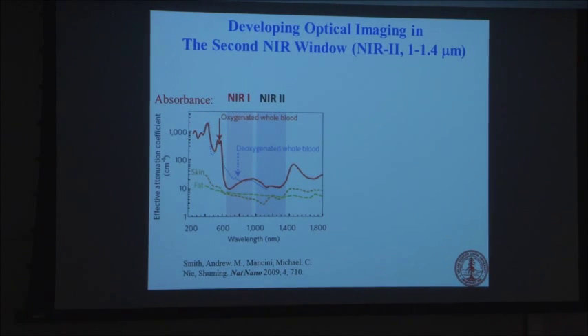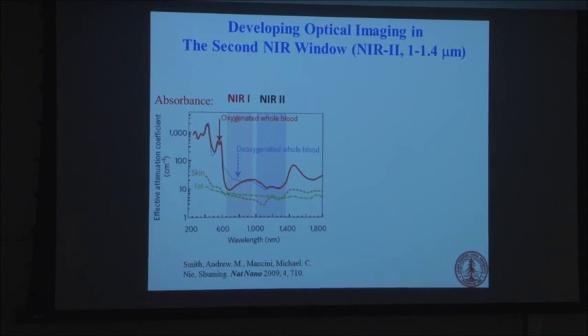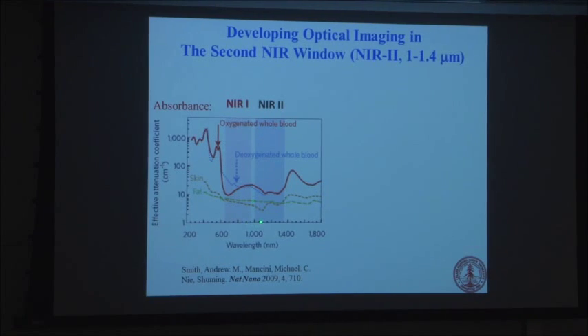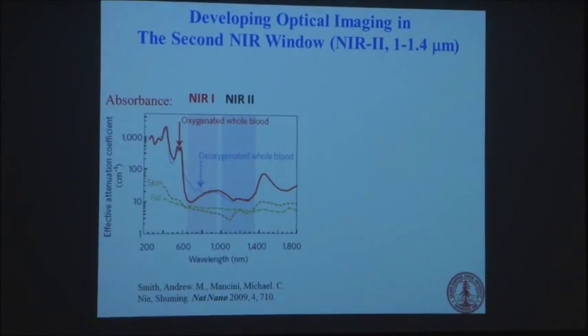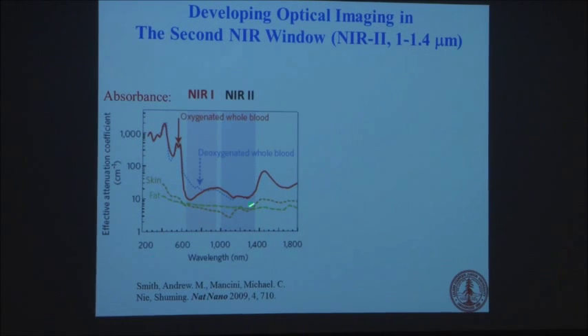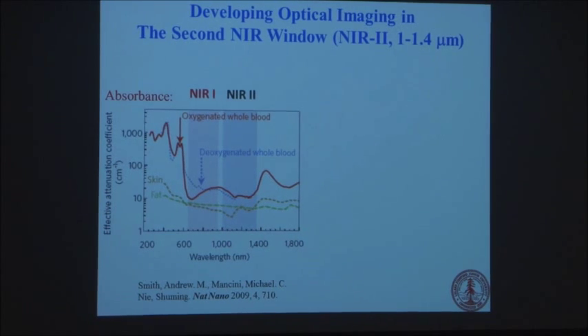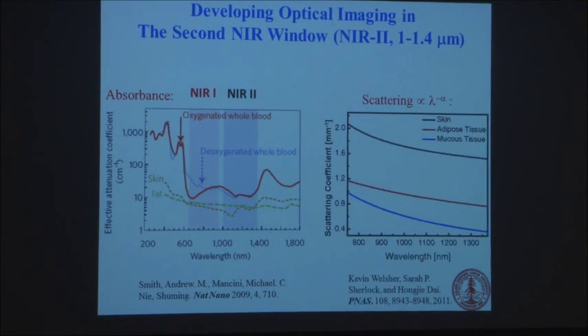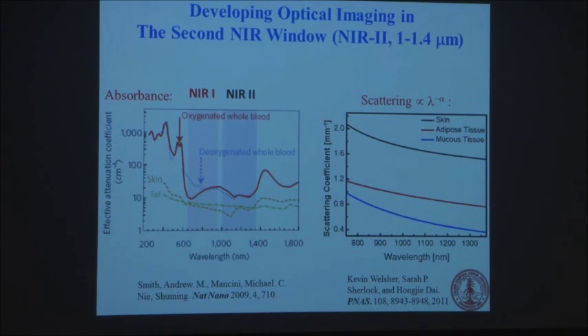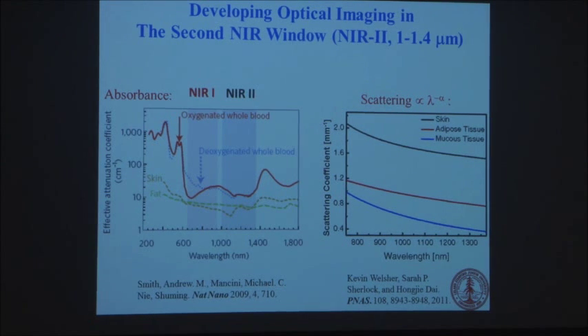We call this near IR1, which is about 800 to 900 nanometers, and then this longer wavelength we call near IR2 because it's a different window. Now these nanotubes are fluorescent in the long wavelength window. And why is that window useful? Simply because scattering is reduced at longer wavelength. Imagine you have light coming from inside of the body, coming out to the outside for detection and imaging. If the light is scattered less, it mostly goes straight out, and then your imaging will give you higher spatial resolution. Otherwise, your image will be smeared.